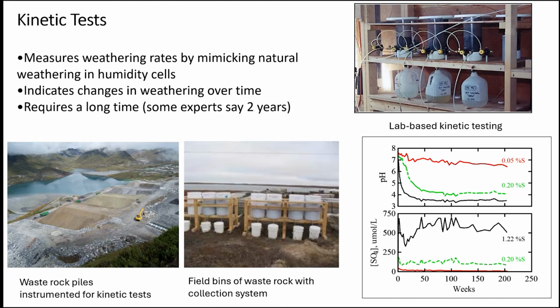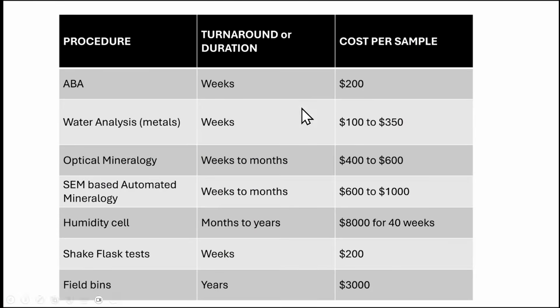This is an academic paper. What you're looking for is a plateau. So you can see if you did the test too soon, you get something that certainly for the pH doesn't necessarily represent any sort of plateau. It's arguable what's happening with the sulfate here, sort of a plateau. But there's a lot of information that can come from these.